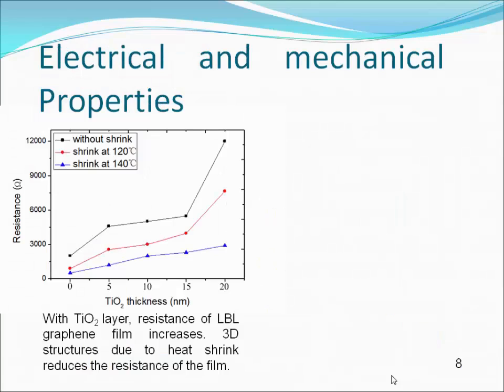Besides that, the electrical and the mechanical properties of these graphene composites can also be tuned and controlled. When the material acts as the functional material of the electrical device, its conductance is very important for the performance. The titanium oxide nanoparticle conductance is smaller than graphene nanoplatelets. So when we added titanium oxide in the center of the film, it reduced the connection of adjacent graphene nanoplatelets. As a result, the conductance of the film decreases.